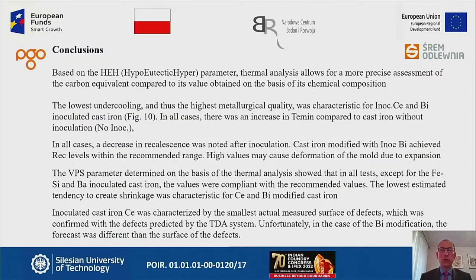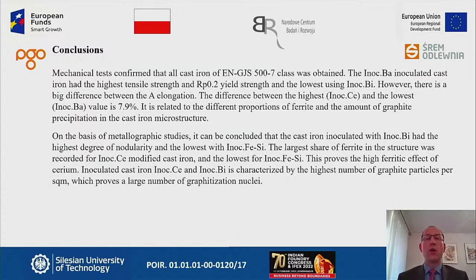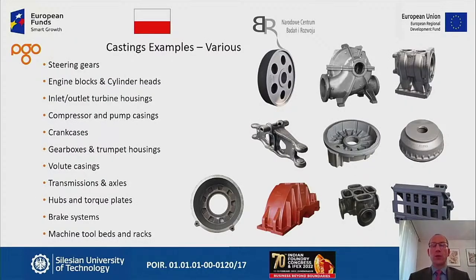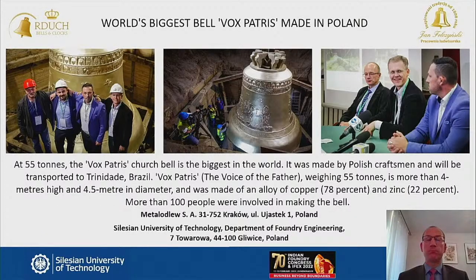And a bunch of conclusions, but the most important one was that we achieved the goal, and we proved that this is possible in real industrial conditions: to control very well the process and to control the metallurgical quality of the alloy before we pour our molds. And we are very happy, and the Foundry is very happy with the results. As I said, we can produce in a very stable way the 500-7 grade of ductile iron, and 600 and 700 as well. So the Foundry now can produce a variety of castings for very demanding clients.